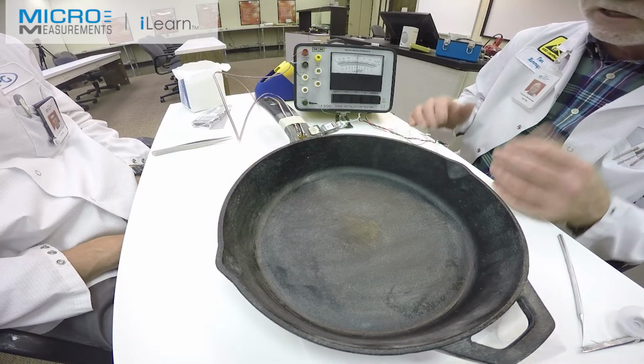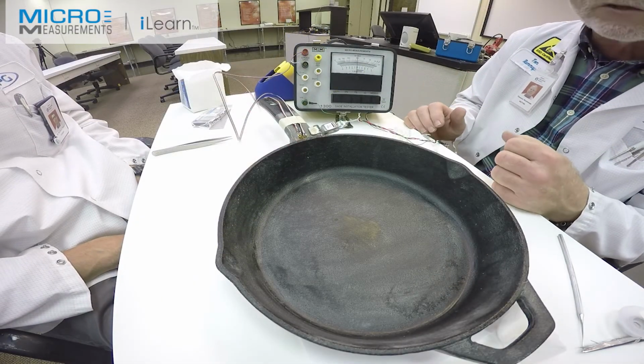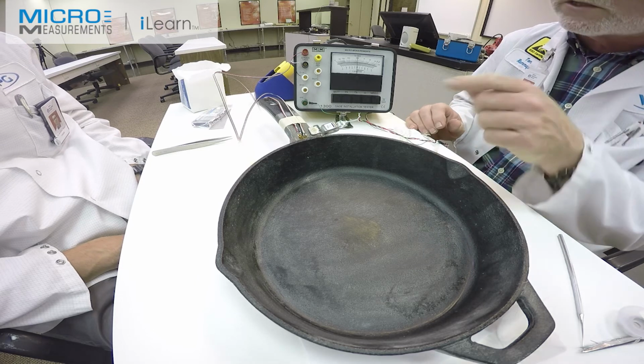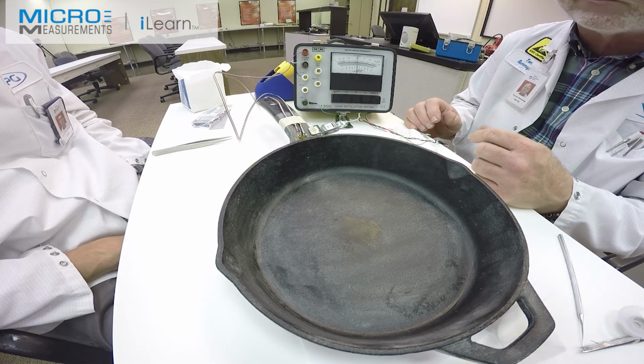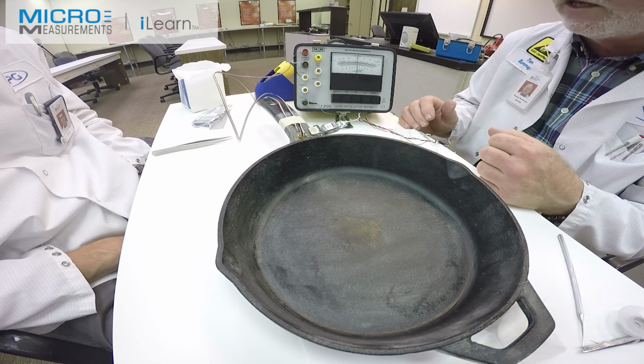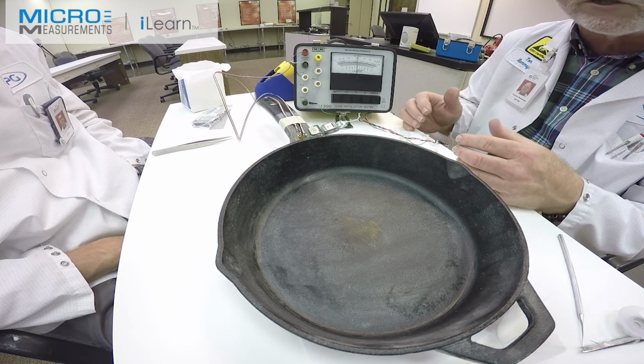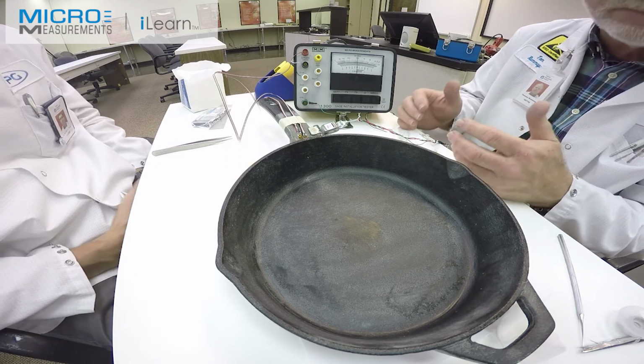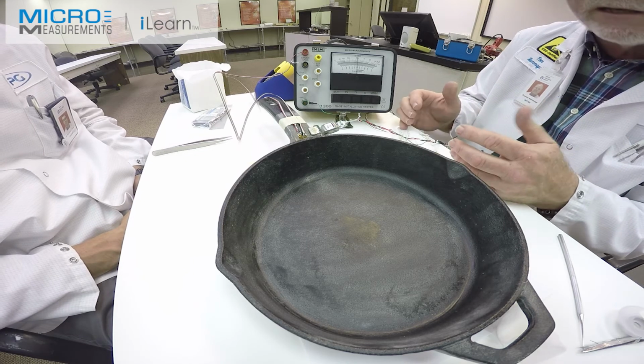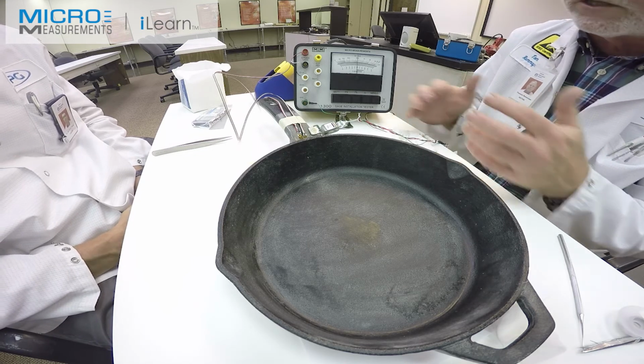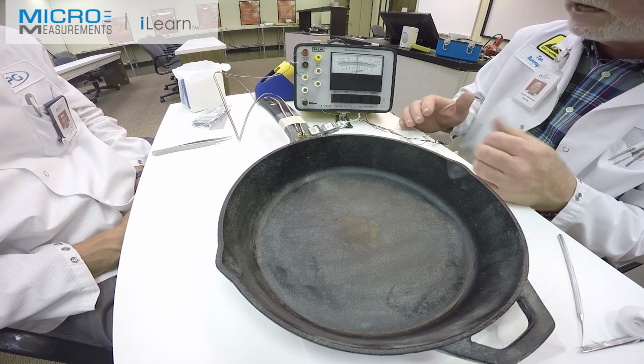Having finished the connection of the lead wires and cleaning up the flux, we need to check two things: the resistance tolerance of the installed strain gauge to make sure it's going to balance in our instrument, and also the resistance to ground, which is an indication of how much we've cleaned up the flux. If we left flux behind, that resistance to ground would cause the gauge to drift or be unstable.